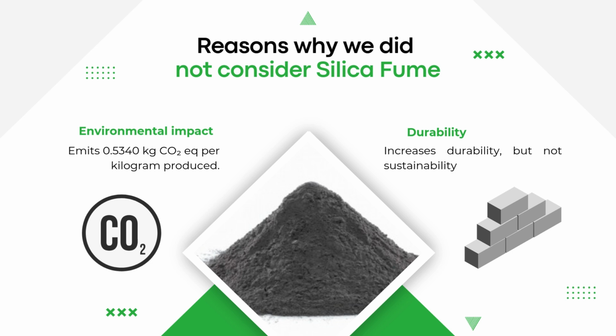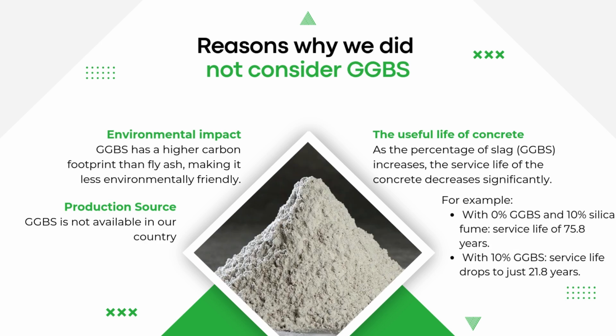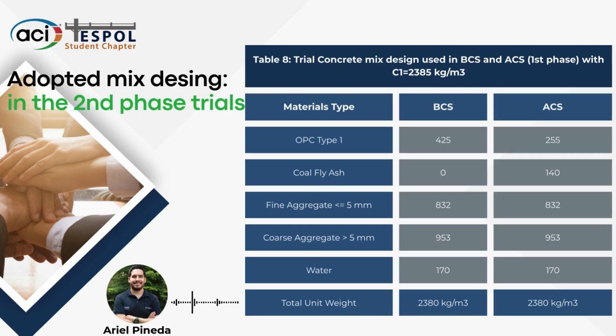We decided not to use silica fume because, despite improving durability, it has the highest carbon dioxide emission among SCMs. GGBS, on the other hand, reduced the service life of the concrete in our analysis, is not locally available, and has a higher carbon footprint than fly ash. Based on the results of the base phase, in this dosage we replaced 40% of Portland cement only with fly ash, as it showed good performance without increasing environmental impact.